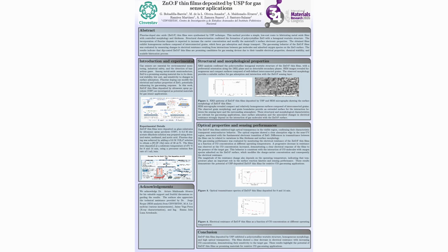Regarding the optical properties, the films show high transparency in the visible region and a clear absorption edge in the near ultraviolet region, which is characteristic for ZnO. Differences between the samples are mainly associated with changes in film thickness and surface morphology.